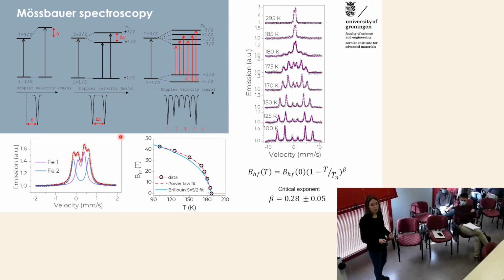So we also know that most of the iron here is in the 3+ oxidation state, which is a good sign, because in the case of oxygen vacancies, which are quite common in oxide films, we would have some iron 2+, while here it was not detectable within the limits of the Mossbauer technique. And then we observed that there is indeed a magnetic splitting upon cooling down, and it occurs at a temperature around 180 K, which is consistent with the SQUID measurements.